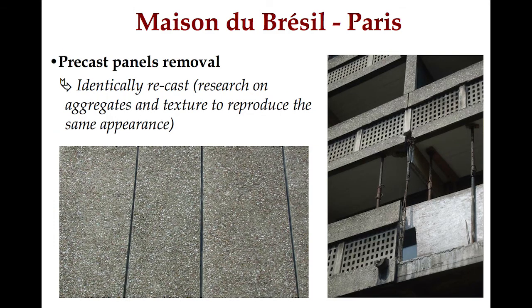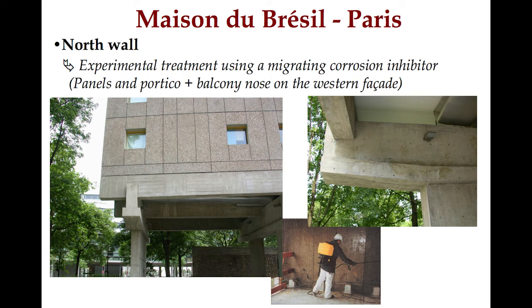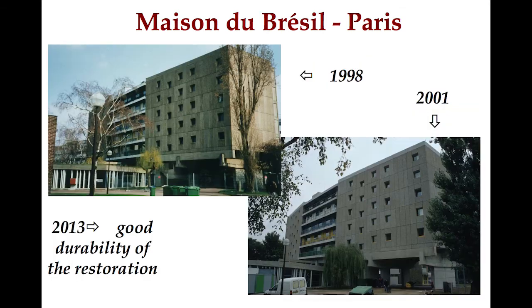And for the precast panels, where there was a removal and identical recasting, there was research on aggregates and texture to reproduce the same appearance. In the north wall, there was an experimental treatment using a migrating corrosion inhibitor. It was for panels and portico, plus balcony nose on the western facade. So you can see here the results before and after the restoration. And in 2013, there is a very good durability of the restoration.